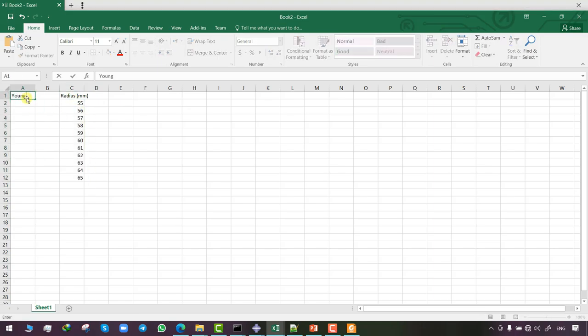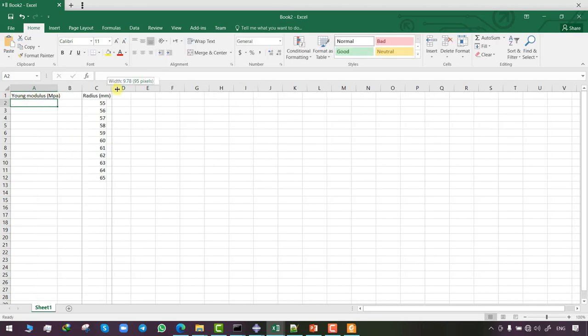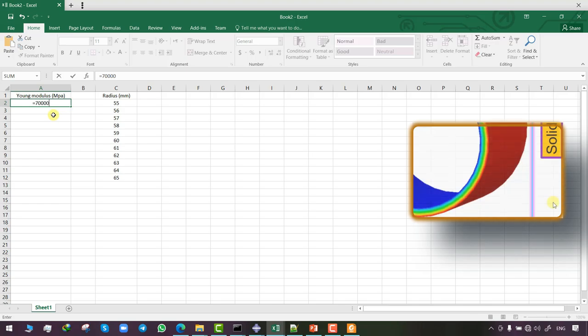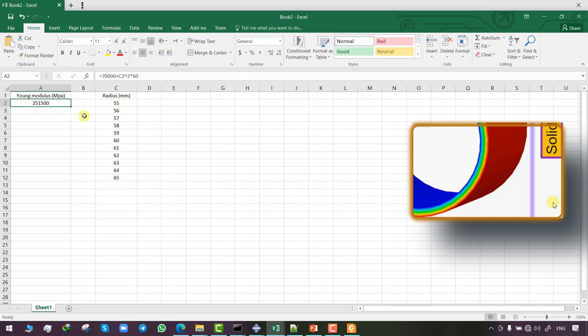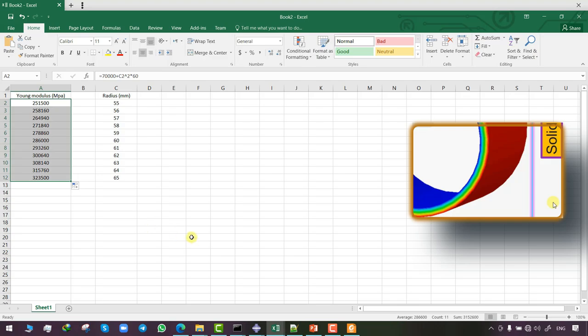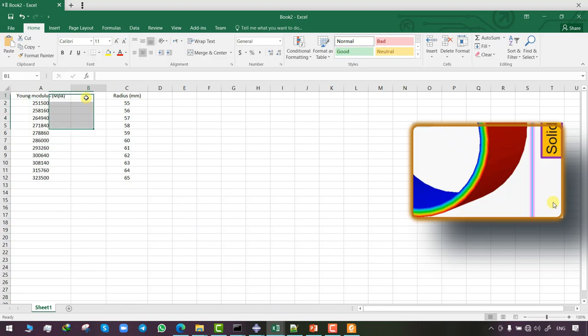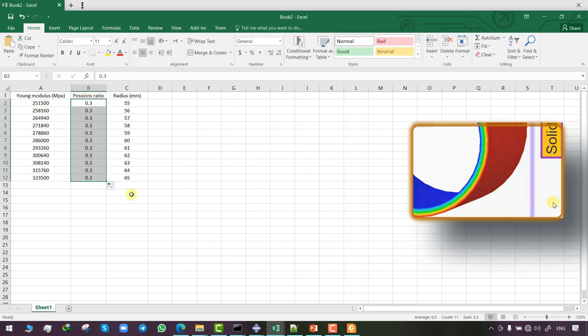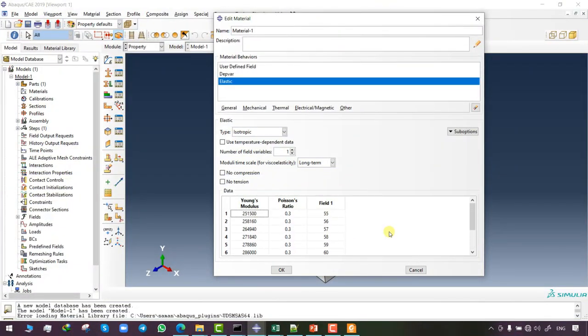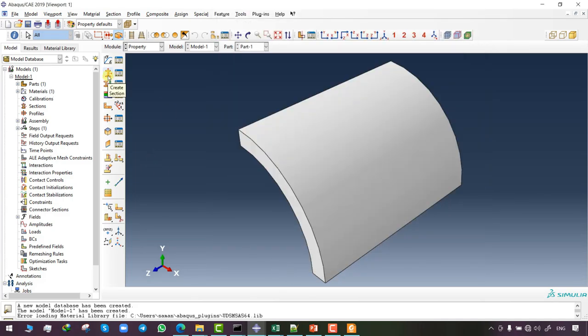In Excel I enter the radius in millimeters from 55 to 65, then enter Young's modulus in MPa. We enter E₀ plus radius squared multiplied by 60, then apply the same equation to every remaining row. Now we have Young's modulus as a function of radius. Since I'm copying this table into Abaqus, I also enter Poisson's ratio here. We then copy the mechanical behaviors of the FGM into the data section.